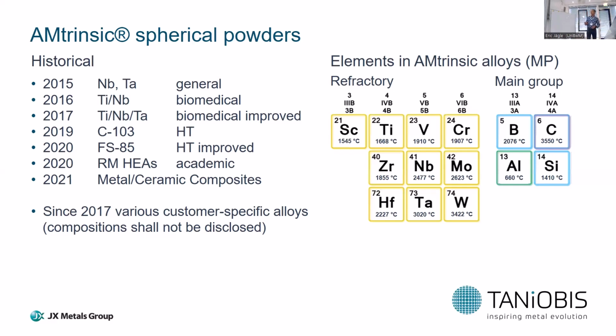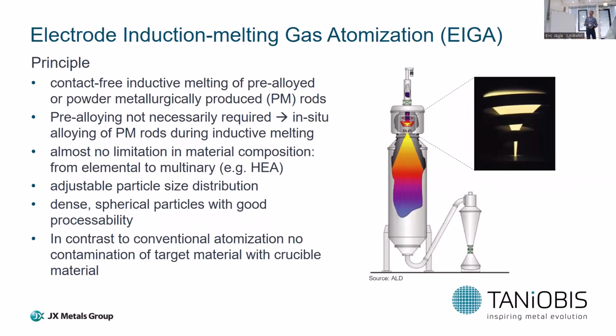The problem with producing such materials is the high melting points, and usually there are no crucible materials available which allow regular gas atomization. This is why we are applying so-called electrode induction melting gas atomization. The principle here is a contact-free inductive melting of either pre-alloyed rods or powder metallurgically produced rods, abbreviated PM, which are sometimes pre-alloyed by sintering, but this is not always necessary. Usually you can also produce simply pressed rods without sintering, because the process itself allows an in situ alloying.